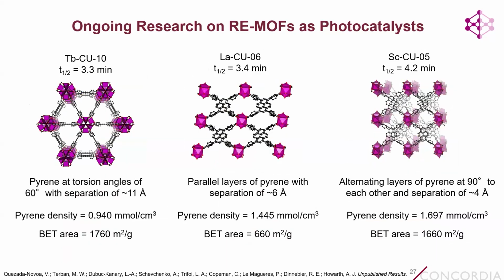And so taking a closer look at the structures then, we thought maybe it's not just the balance between pore aperture size and pyrene density, but it must also have to do with the arrangement of pyrene photosensitizers and specifically their spacing distance. And so if we look at terbium Cu10, for example, we have pyrene in this structure that is angled at about 60 degrees from each other with a separation of 11 angstroms. And so we think that this separation in this structure should be enough to hinder, or at least partially hinder, excimer formation in these MOFs, which can be a competitive pathway for the generation of singlet oxygen.